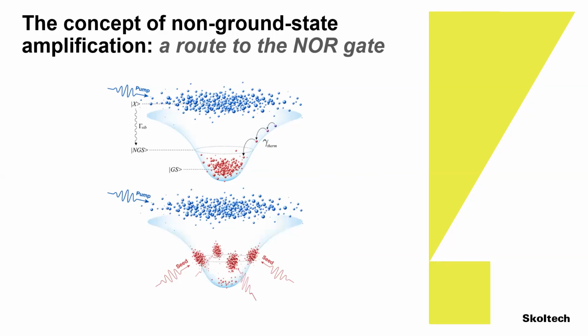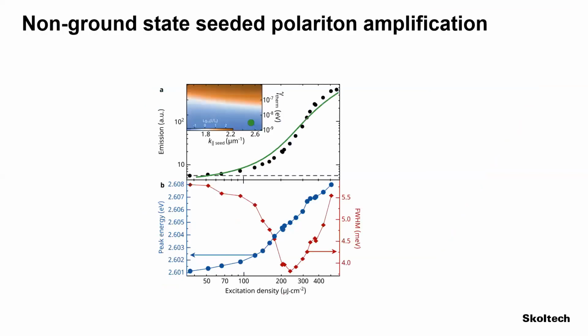If I rotate the parabola that I was showing you before as the lower polariton dispersion, I can put more of one of these control or seed beams to create seed amplification at the non-ground state. So really the proof of concept is to show that I can amplify a beam not at the ground state of the polariton dispersion. And this is what we set out to do. We studied numerically, as a function of the thermalization in the system and the in-plane momentum of the photon that we inject, where we can really compete with condensation and get amplification of a non-ground state. And it is actually quite stringent conditions.